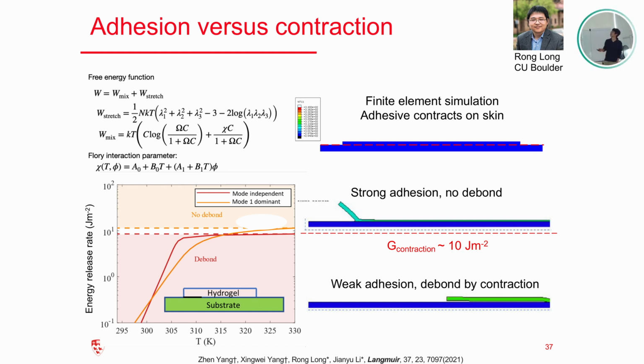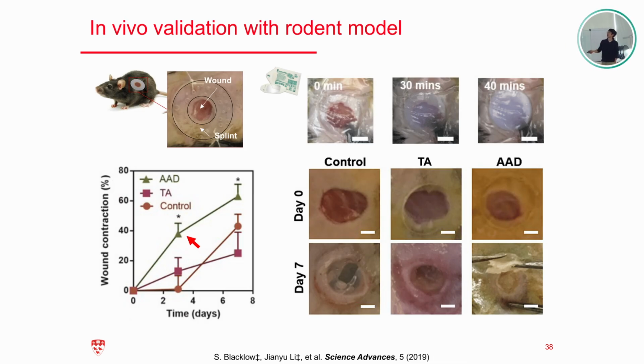without delamination. Just a quick result about the in vivo test: we're testing this using the mice model, and we quickly show that by having this active contraction function, we can accelerate the wound closure. On day 3, we can close nearly half of the wounds, but in the control cases, using Tegaderm or non-contracting adhesive, we have very small contractions. And this speed is independent of biological process, and we believe it's because of this mechanical effect.